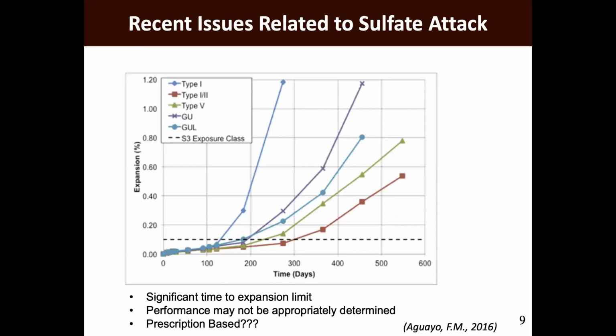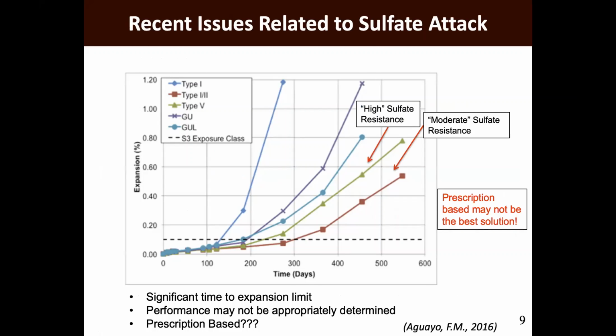So we've done a lot of different data over the many years. We've done testing over 15 years on sulfate in both field and lab. And if you look at performance-based specifications and performance cements, what you have here is basically variations of different sulfate resistant cements. And what's interesting is that you have a high sulfate resistance actually performing worse than a moderate sulfate resistance. And so that's indicating, right, that prescription may not be the best solution.